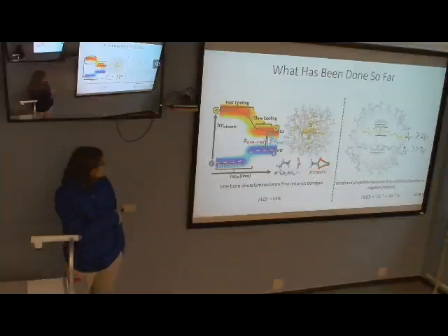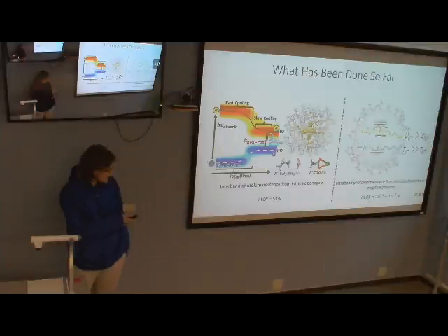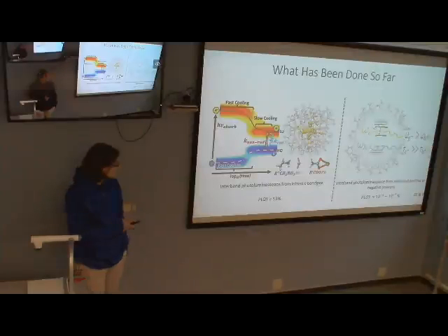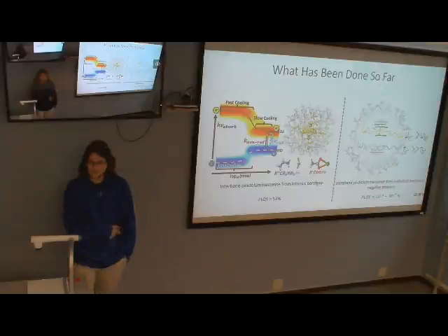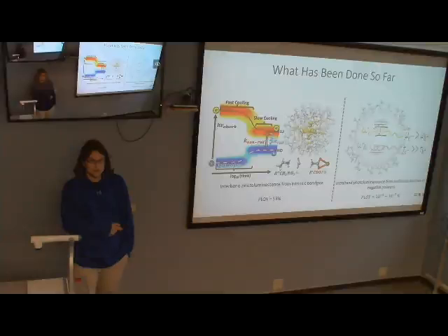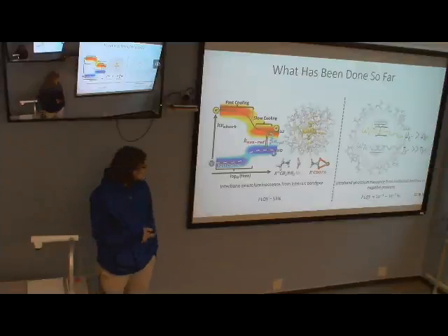Essentially what we measured is, based on the initial state, the hot carrier dynamics as it cools from a non-equilibrium position to the band edge. And then from there we modeled its luminescence properties and calculated a theoretical photoluminescence quantum yield by calculating radiative and non-radiative rates of relaxation from the band gap. That gave a reasonable approximation to what people see in experiment. Usually in experiment they see a little bit higher yields, but it's not a one-to-one comparison because this model is a little smaller than what's seen in an experiment. But we have the right order of magnitude, so that was a sign that our methodology seems pretty robust to describe these systems.